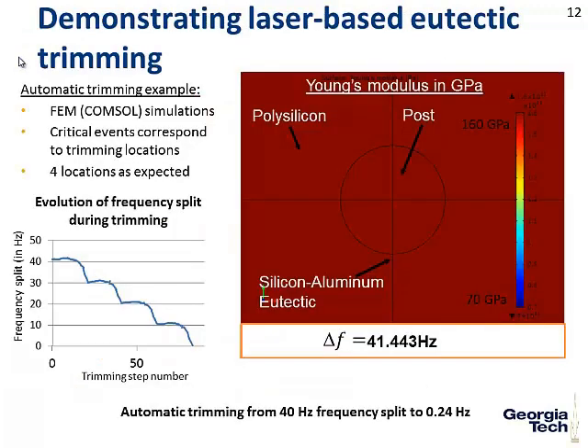Here is a simulation in COMSOL where I created a frequency split of 41 hertz. And you can see here that I'm modifying the stiffness, so the Young's modulus in this case. And you're going to find that there are 4 locations where the frequency split went down in an important manner. Those 4 locations correspond to the 4 locations in red that you could see around the post. Also, you'll see that sometimes the color becomes red, and they're at the 45 degrees location, and this corresponds to the other color, the blue color.